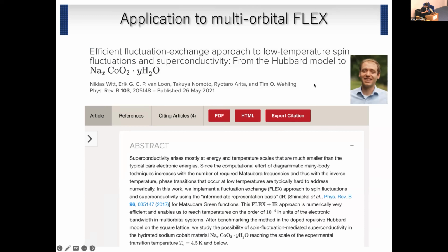And so in this paper, we solved and obtained the TC of the 3-orbital Hubbard model. In the standard approaches, the numerical cost to solve the FLEX is quite high. So calculation for temperatures lower than 1 Kelvin, for example, is numerically very expensive.